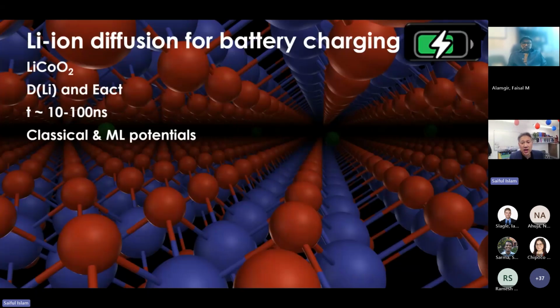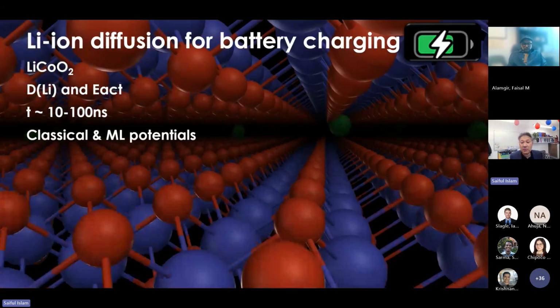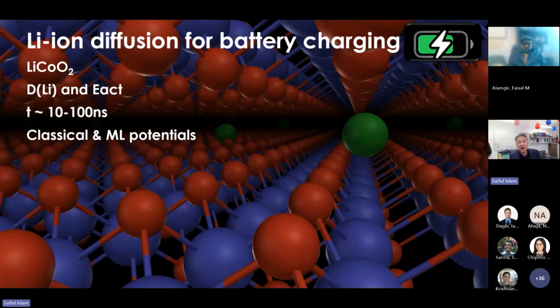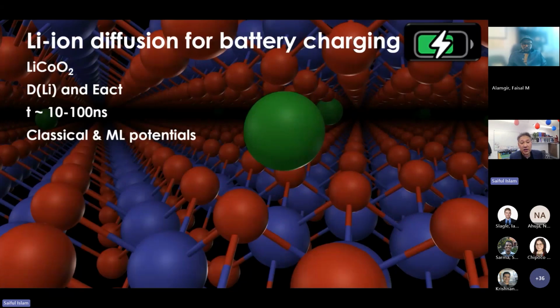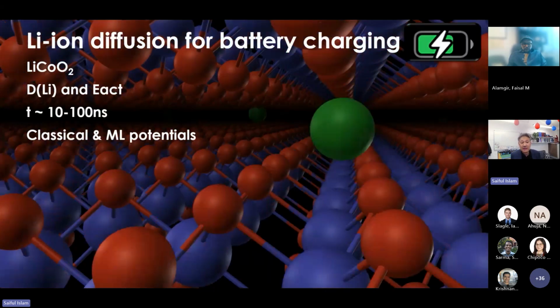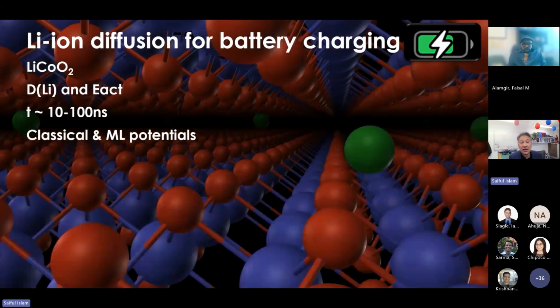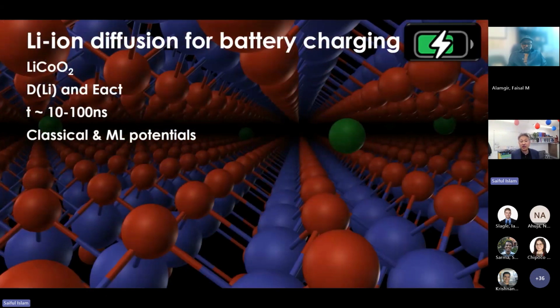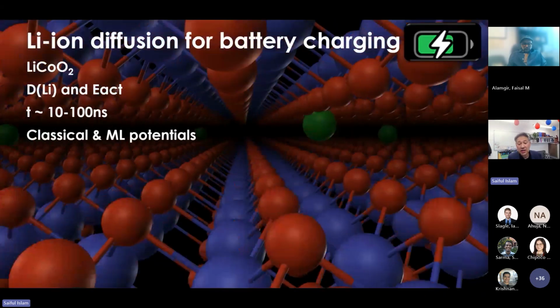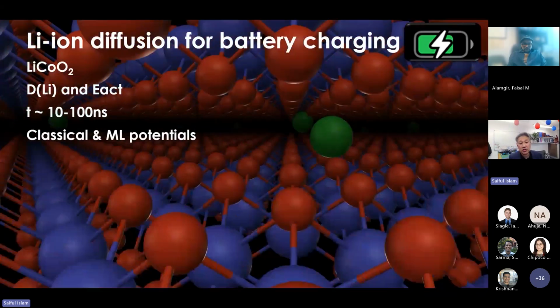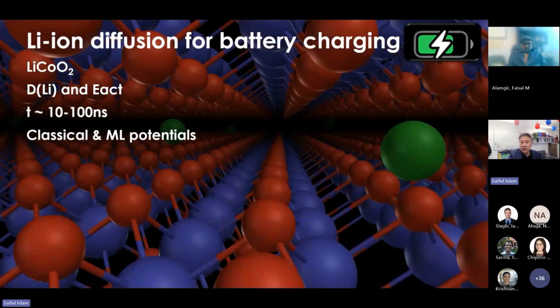We model the lithium cobalt oxide to look at the lithium diffusion properties. So those keen followers of solid state chemistry or material science will know the oxygens are in red, cobalts are in blue here, and you'll see that the green are the lithium ions. And what we can get out from these simulations are the diffusion coefficient for lithium, activation barriers from Arrhenius plots. But from these large scale MD, we can run up from 10 to maybe even 100 nanoseconds, which we can't do using conventional DFT techniques. So these are using classical and machine learned interatomic potentials.